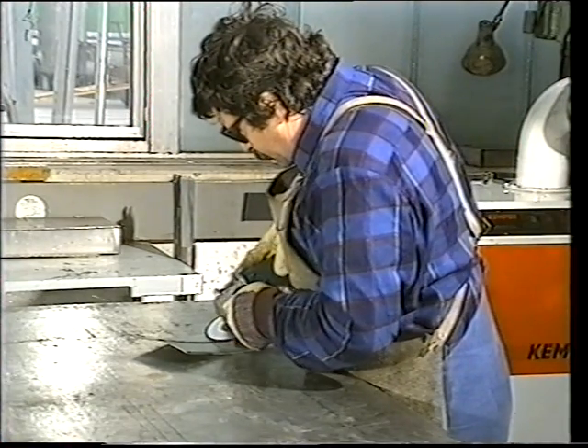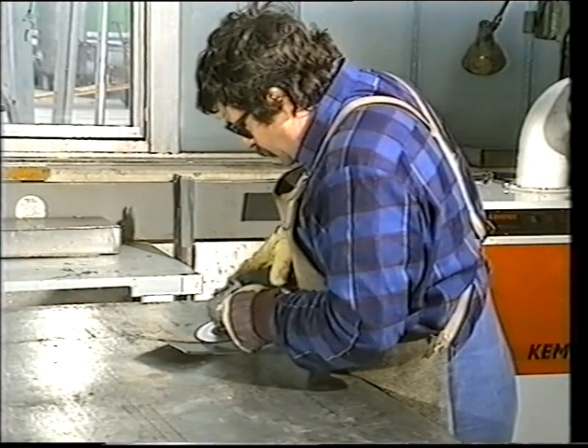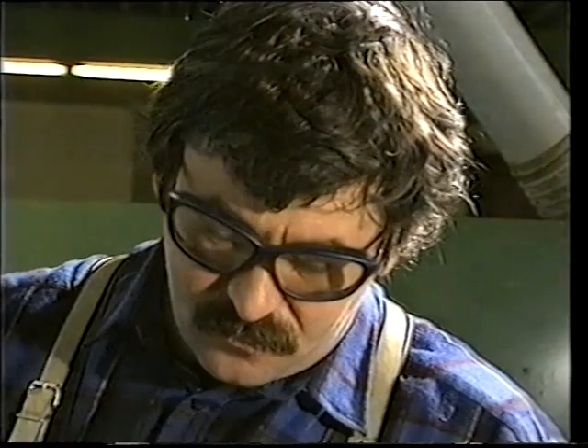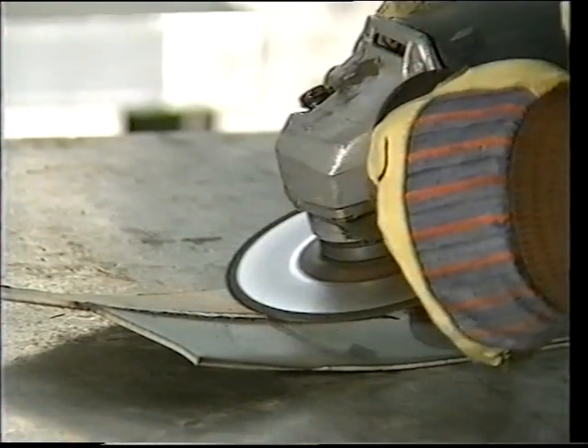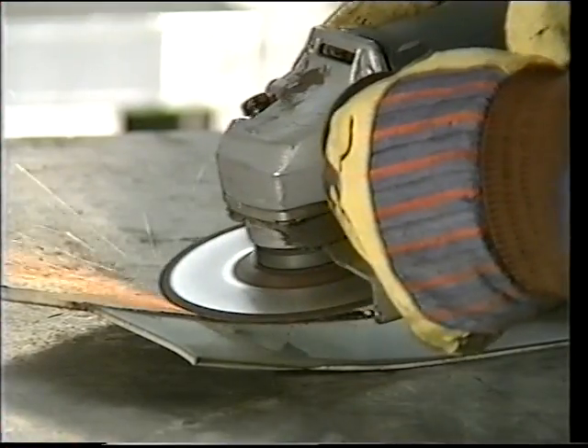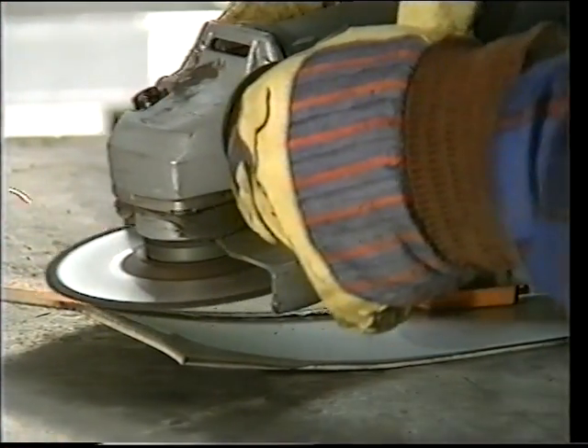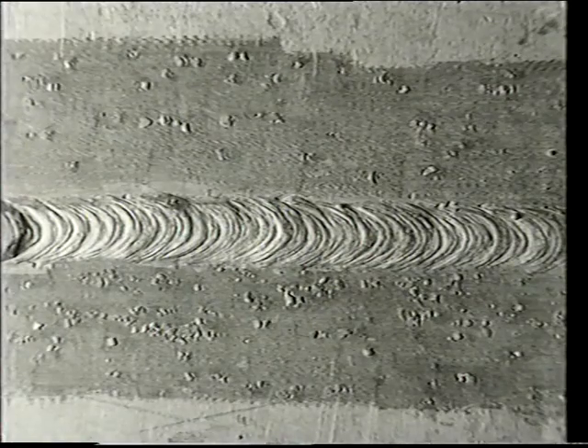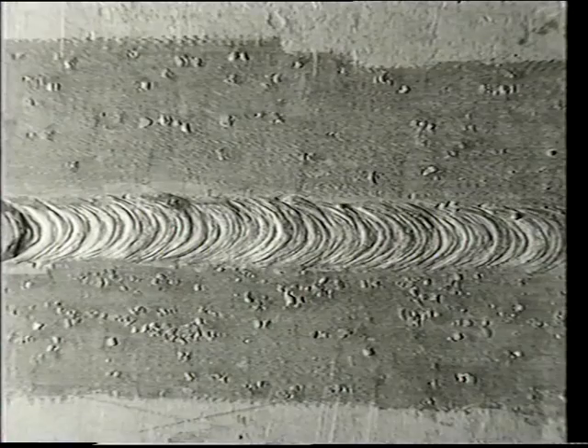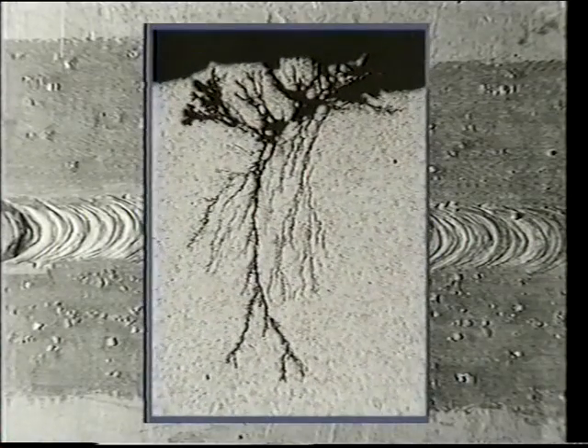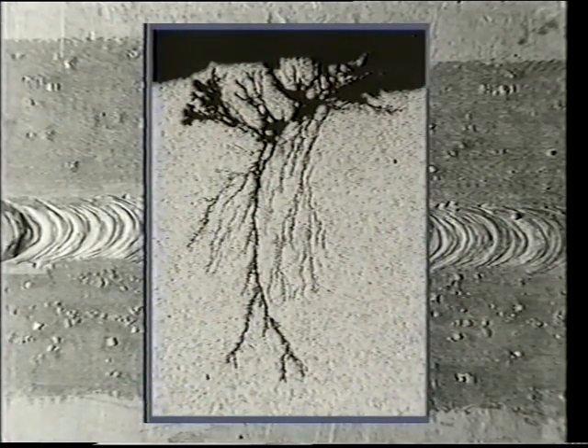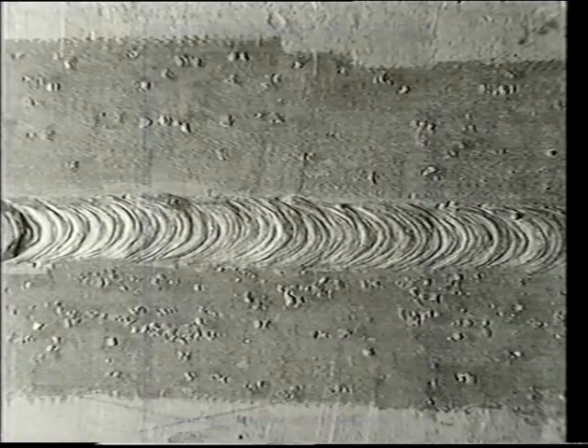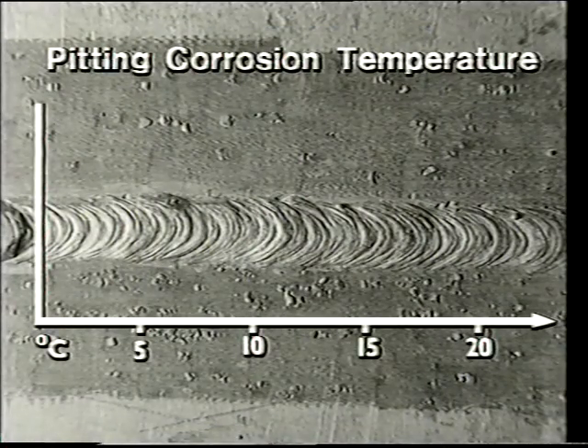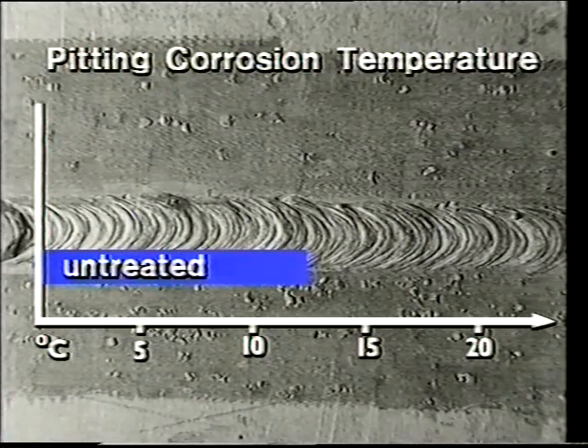One simple method is grinding, but that is highly problematical and unsatisfactory in terms of corrosion. High removal rates cause surface stresses, leading in turn to stress corrosion cracking. Any substance containing chlorine will then cause blistering. The cross-section shows how deeply corrosion has penetrated after only a short period of time. Laboratory tests confirm that in a 10% iron chloride solution, the untreated weld will resist corrosion longer than a ground weld.